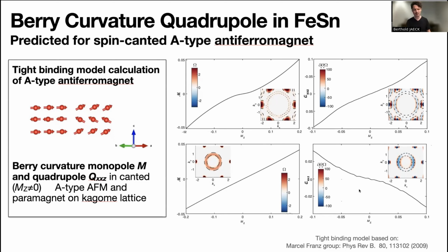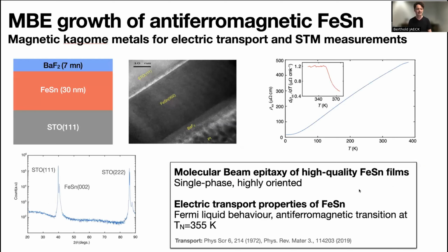So with this understanding of the basic magnetic and topological properties in our pocket, we went on to synthesize thin films of this compound. We adopted a growth recipe from the Checkelsky group, where we grow thin films of iron tin and protect them with a capping layer of barium fluoride. When we realize this growth, we end up with very uniform, nicely ordered films that crystallize in a single phase. They're not necessarily single crystalline, but we don't observe any other phases, such as Fe3Sn2 or FeSn2, and so on.